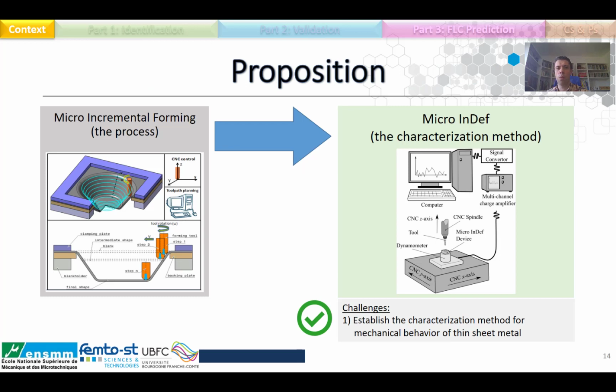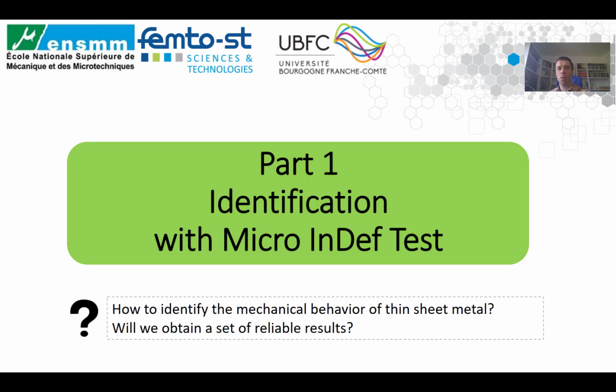As I have shown in the previous slide, classical characterization methods didn't fit all the requirements we have for this project, but micro-INDEF test did fit all of them. So we propose to use micro-INDEF test as a characterization method. Micro-INDEF test is inspired from micro-incremental sheet forming. The first part of this presentation will explain the identification method, and will show that the results we obtain with this method are reliable.